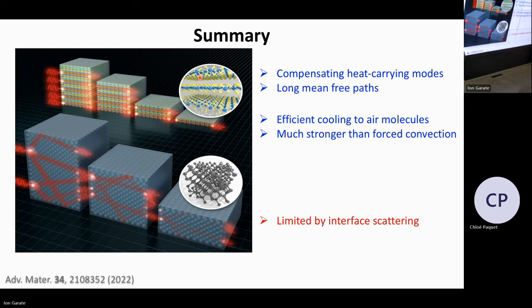So here we get to the rest of the explanation. Basically the idea is that in a layered material, the phonons are already mostly in plane, because they're like these internal interfaces. So there's not a lot of diagonal phonons moving through the system. So if you then start thinning down, there's not a lot of additional scattering at the surface. You do lose a few modes, but they're compensated by these additional flexural modes that come in. And that then gives you this flat thermal conductivity as a function of thickness.